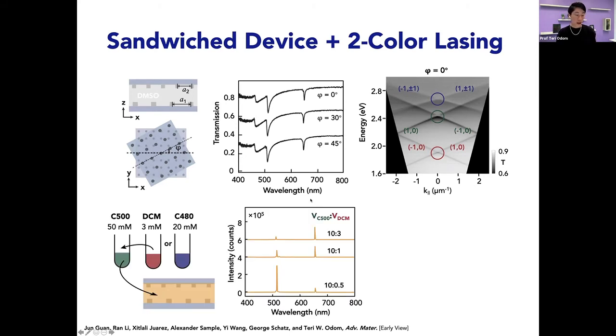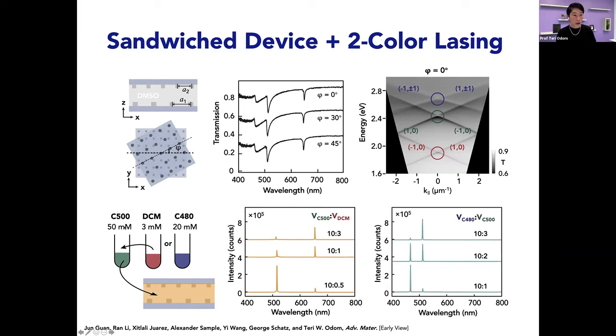So then we decided to start having these 2 sandwich substrates, and then mixing dyes in the interior. So first, let's focus on the DCM added to C500. And again, you can see by controlling the volume ratios, then you can have higher intensity lasing emission at shorter wavelengths or higher intensity lasing emission at longer wavelengths. If we combine C480 with C500, you can see everything shifts to bluer wavelengths here, bluish greenish wavelengths. And then again, by controlling the dye volume ratio, we can get different intensities of color. This is pretty neat.